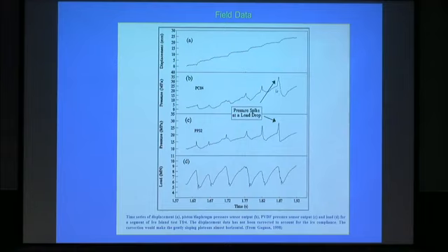This is pressure data from two types of pressure sensors here, the diaphragm type traditional ones and then the piezoelectric ones that Kai referenced. And in each case you see these spikes that occur. The spikes are associated with that transfer of load. When a spall breaks away, the load transfers to the remaining ice and you get a spike in pressure very fast. And this is the load record for that.